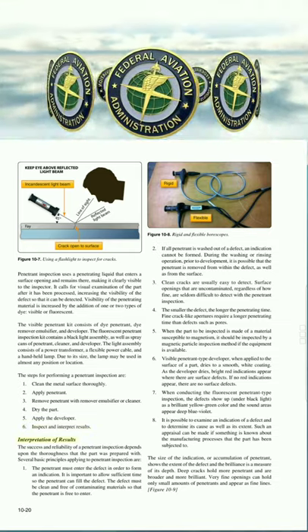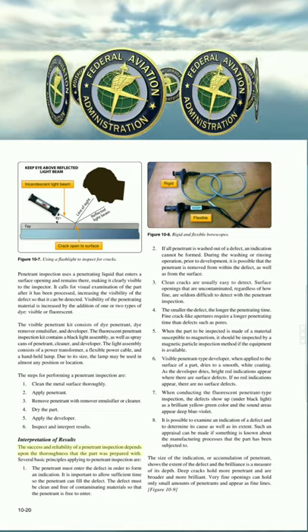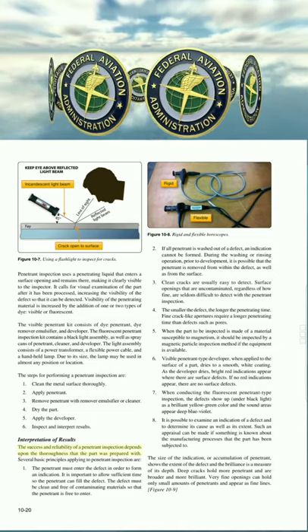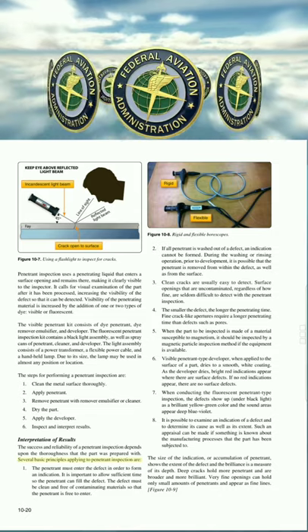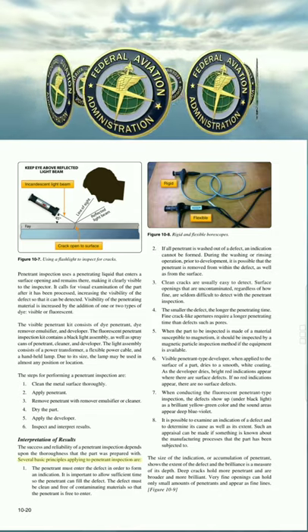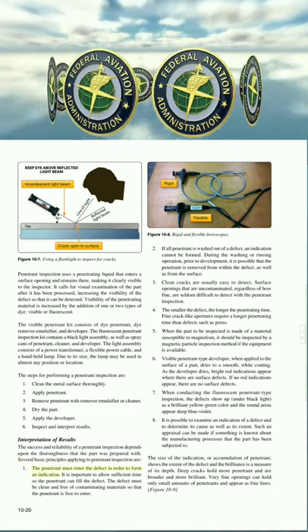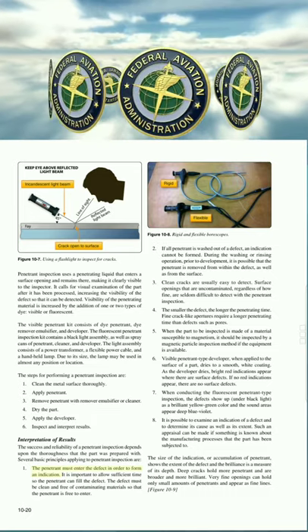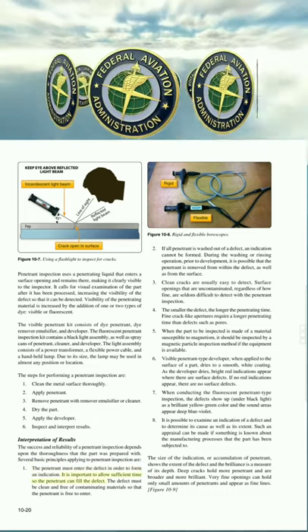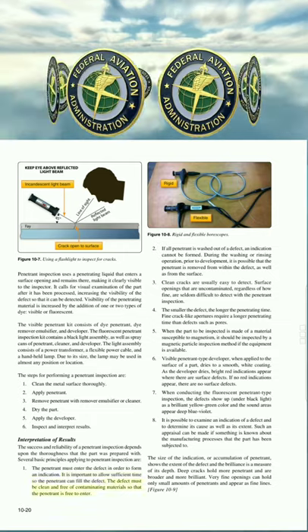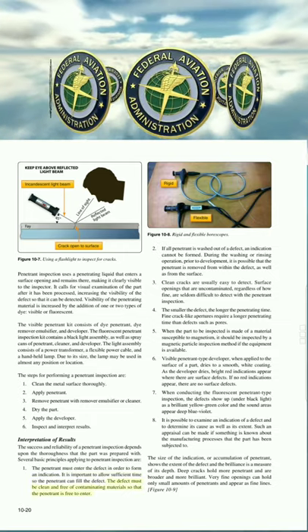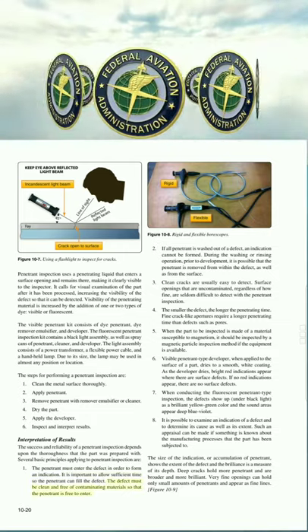Interpretation of results. The success and reliability of a penetrant inspection depends upon the thoroughness with which the part was prepared. Several basic principles applying to penetrant inspection are: 1. The penetrant must enter the defect in order to form an indication. It is important to allow sufficient time so the penetrant can fill the defect. The defect must be clean and free of contaminating materials, so that the penetrant is free to enter.